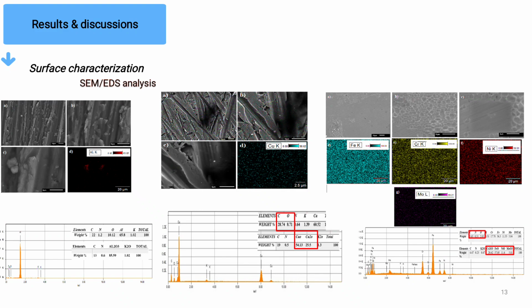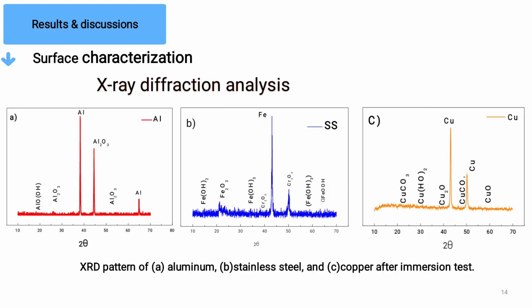The SEM analysis of copper showed a corrosion product on its surface. The fatty acid composition and the profile of biodiesel play a critical role in activating oxygen atoms in biodiesel, leading to the metal oxide formation. The X-ray diffraction analysis showed a significant oxide formation on aluminium, stainless steel, and copper surfaces in biodiesel. Aluminium exhibits a robust protective layer of aluminium hydroxide and oxide, resisting biodiesel-induced acid corrosion, while stainless steel and copper showed a significant oxide formation, indicating a corrosion process.